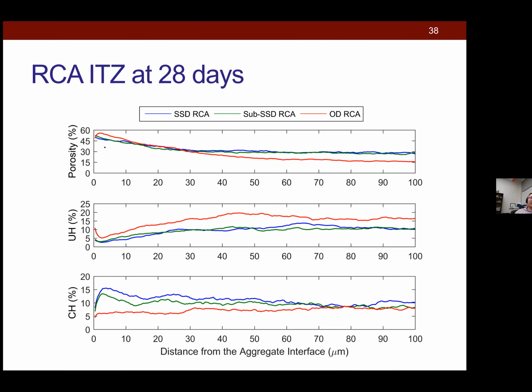So if you do look at studies that have looked at these different moisture contents, we find, again, there's a lot of variability. Typically, your best strength and best durability concretes are when your RCA is at this sort of sub SSD condition. So kind of like 80% SSD. So it still absorbs some moisture from the microstructure, right? One idea is that it kind of sucks in also some cement paste, and so you get this sort of better mechanical interlock.